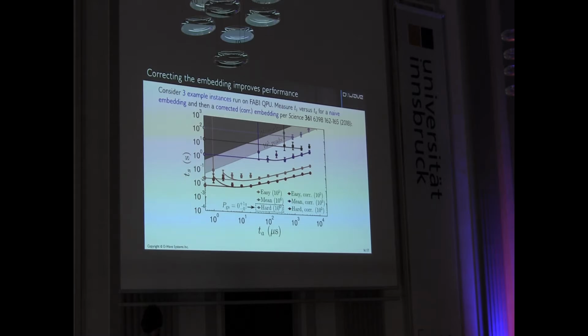So in all 3 cases, you can see things got better. Not so much for the easy instance, it didn't seem to do much for me, but clearly once I get to the mean instance, it's dropped things down quite considerably. And lo and behold, certainly within 100,000 reads, I've been able to see that hard instance now. So we now actually can pull out solution times for all three cases.